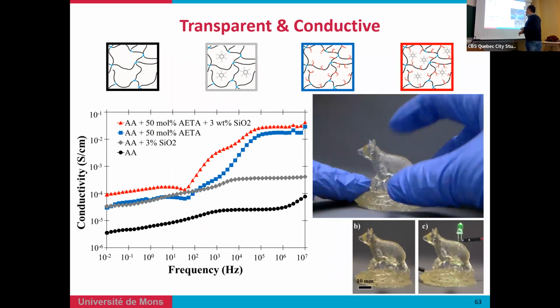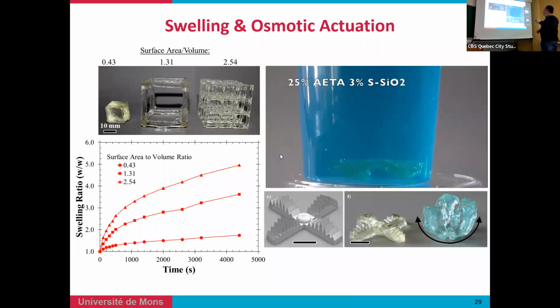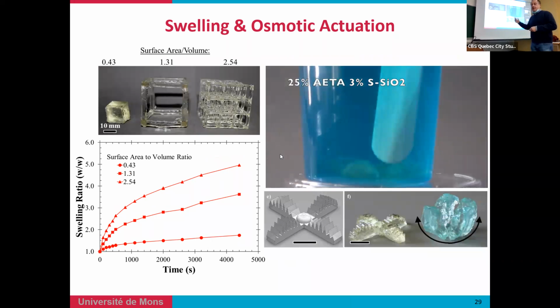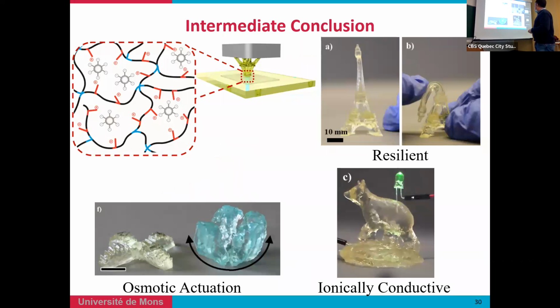Also, based on the fact that you have some ions inside the system, you can have a certain conductivity, as shown here. If you put an electrode and a diode and apply a certain current, you can see that you can light the diode based on the conductivity of the samples. Of course the actuation can also be maintained, because in this case, if you play with a certain geometrical anisotropy, we can have actuation as already shown previously.